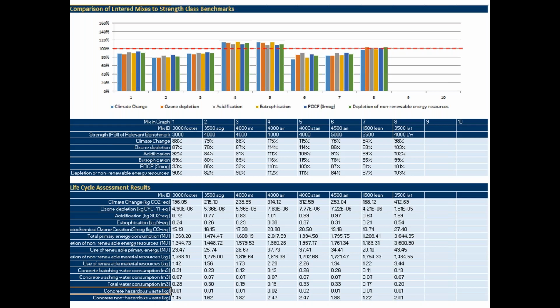So going on that, we're going to use this as an example. This is a different project, but in this case, using the LCA calculator, we have footings, slab on grade, interior concrete, exterior 4,000, 4,000 stair pan mix, 4,500 exterior concrete, a lean concrete, and then a lightweight concrete. All those were put into this, and we're comparing it to the industry benchmark for the NRMCA. In this case, it was using the Great Lakes as the region. So when we look at this, we could see that mix 1, 2, 3, 6, and 7 would go towards that credit of the multi-attribute application showing the lower numbers.